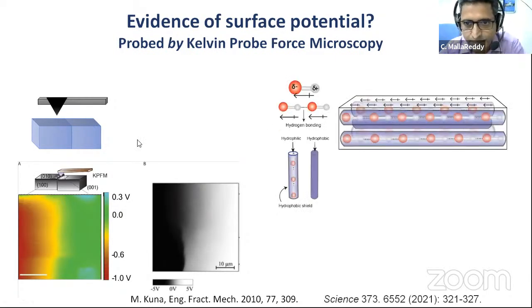When we did the experiments on the perfectly healed crystals, we did not see the gradient. We saw some potential, but it was not a gradient from positive to negative. So that tells that when these crystals heal perfectly, you don't have remnant charge and you don't have this charge gradient. That means there is an advantage if it heals properly. If it doesn't heal properly, it doesn't optimize the charges properly, so there is a penalty. This basically drives the crystals to achieve very good self-healing, and probably that is the reason we don't see any sign of a crack when these crystals properly heal.